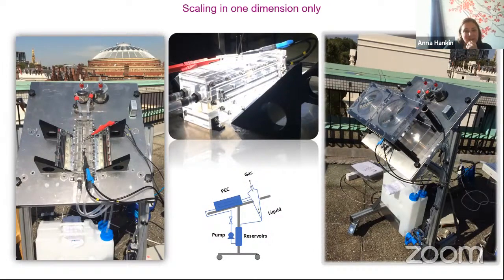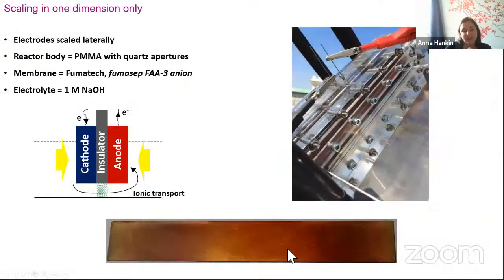So on one side, we had hematite, about 15 by 4 millimeters, made by spray pyrolysis on titanium. The structure, if you look at it sideways, is one of those suboptimal structures that I talked about, in the sense that if you were to make the electrodes taller, you would start to have the non-uniform current density distribution. But in this case, we made the electrodes sufficiently short. So, long in one dimension, but short in the other dimension, so that this effect wasn't very pronounced. And we used COMSOL to check that it would be roughly okay. We had an anion permeable membrane and some sodium hydroxide.